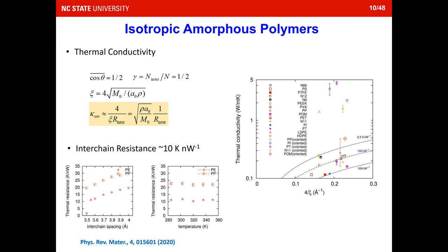Just please ignore the top dots because they're not isotropic amorphous polymers. The bottom lines are all the amorphous polymers. And you can find that if you use the interchain resistance on the order of 10 Kelvin per nanowatt, it actually fits all the experimental data pretty well.